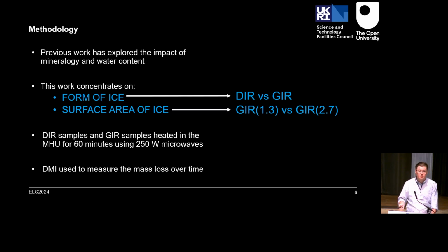As I mentioned, the first paper I produced looked into the adjustment of water content and the mineralogy of the simulant. So I wanted to look at, firstly, how the form of ice affects the water extraction, diffuse ice versus granular ice. And from the first paper, I found that the surface area of the ice had an impact on the water extraction. So I wanted to look into surface area, and that's why I've got the two different grain sizes. With the diffuse ice, it's very difficult to quantify the surface area, whereas with the individual grains of ice, we can make an assumption of what the true surface area is. Apart from that, the experiments were kept consistent. I heated them in the microwave heating unit for 60 minutes using 250-watt microwaves, and then I used the mass instrument to measure the mass loss over time.